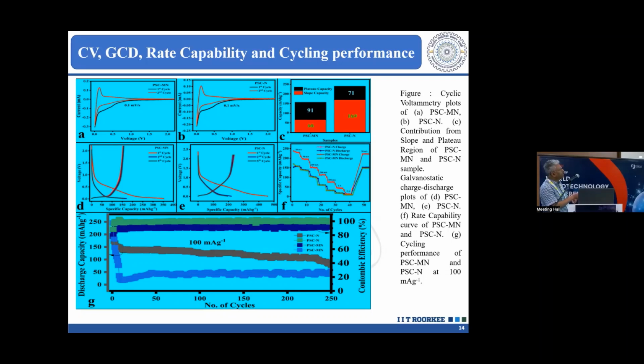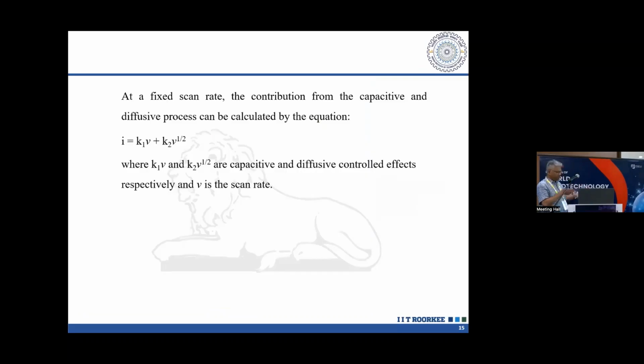So that was the observation made, and then what is the diffusive control and the slope control, this diffusion and the slope. This comes from the capacitance from the plateau behavior, and the capacitance that comes from the slope behavior. These were estimated and plotted here, along with the Coulombic efficiency, as well as at different current rates. If we do this, how the capacity varies, and it is fully reversible. When we go from this current rate back to that current rate, it almost equalizes, not exactly, but it goes like this. So all these tests were done in order to make the material usable as a good anode material.